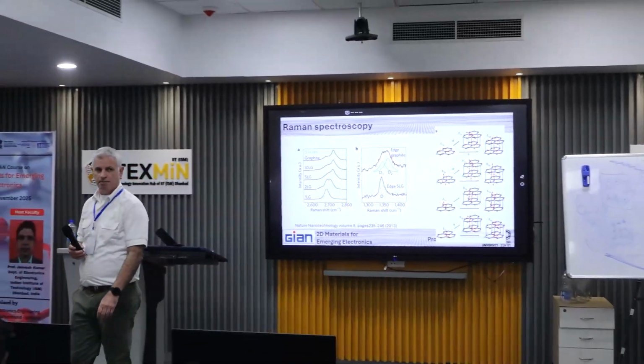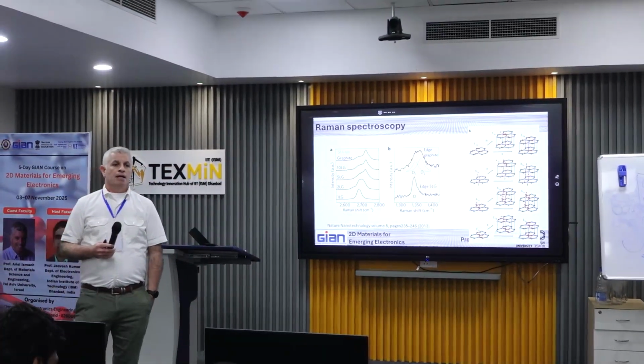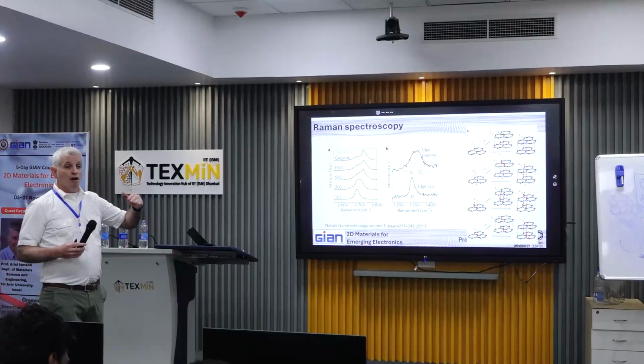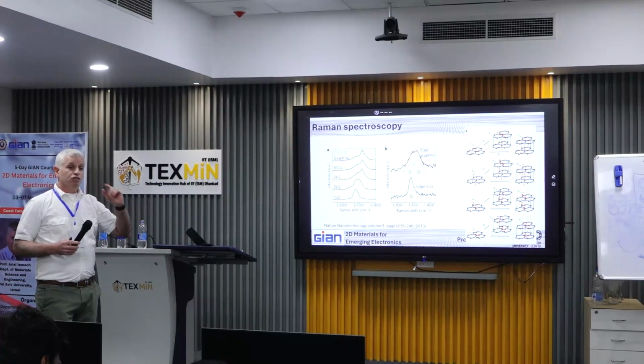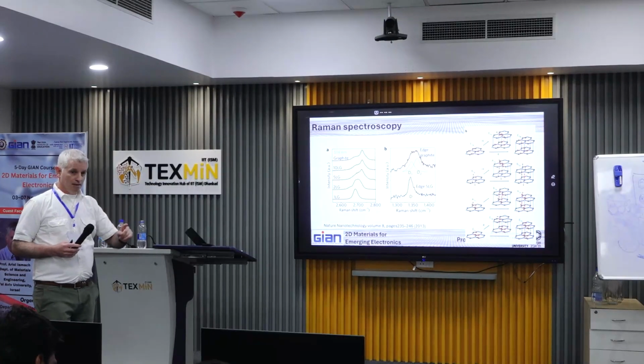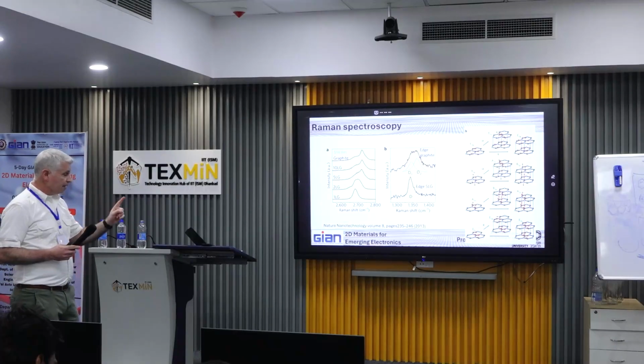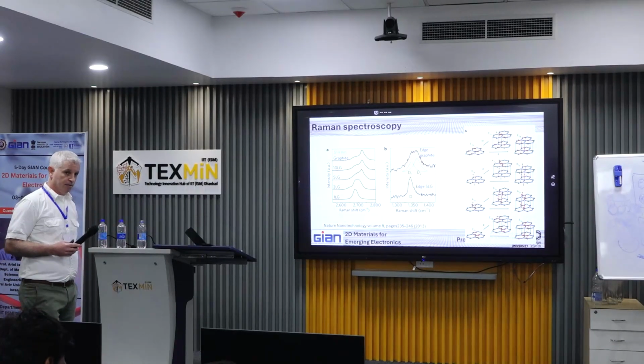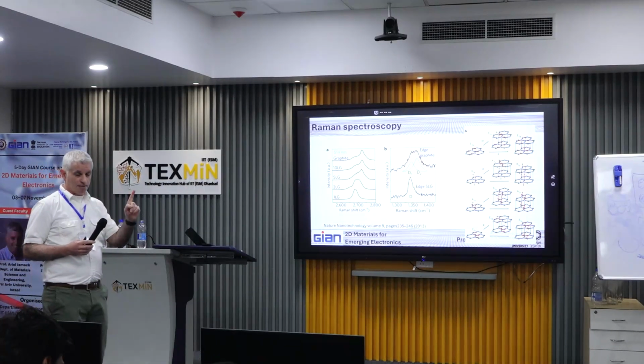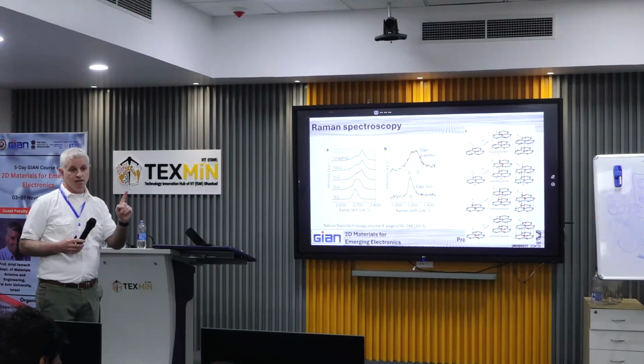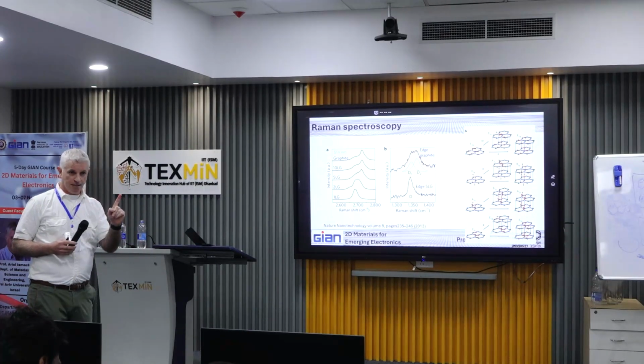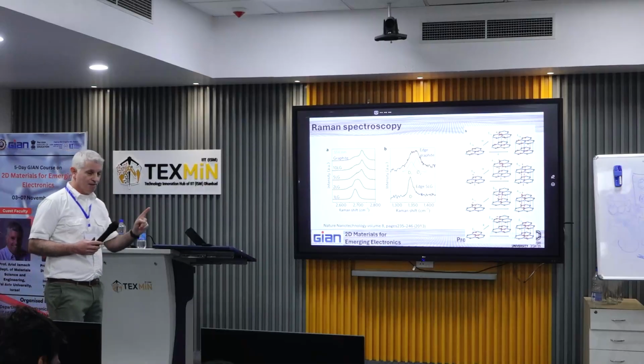So there are various G points. In multi-layer, you have several contributions to the G prime, which is the 2D band. Yes, in the single layer, you have only one G prime. And that's also a characteristic signature of a single layer profile. But you need to be careful.